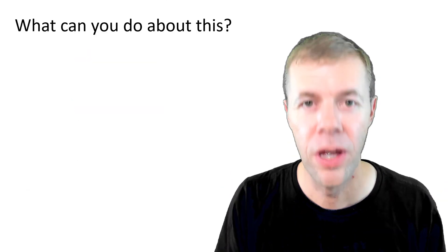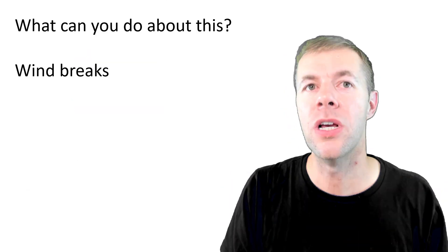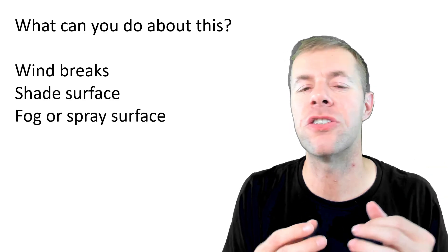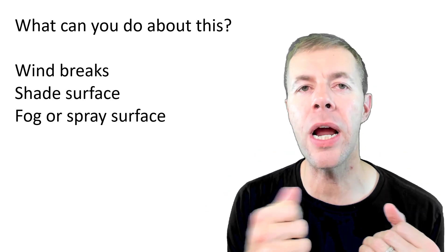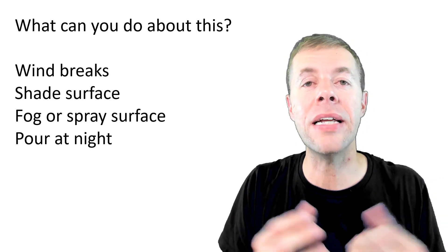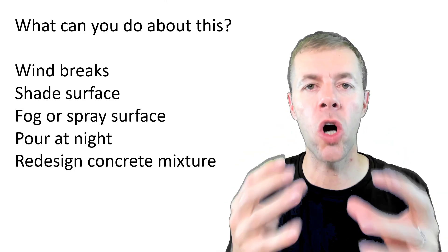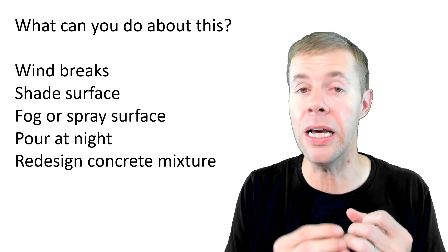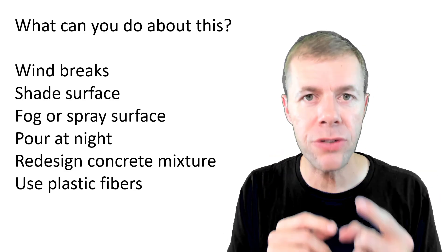So what can you do about this? You can build windbreaks, shade the surface, fog or spray the surface to try to keep it cool. You can pour at night. You can actually redesign your concrete mixtures. That would be a great idea.